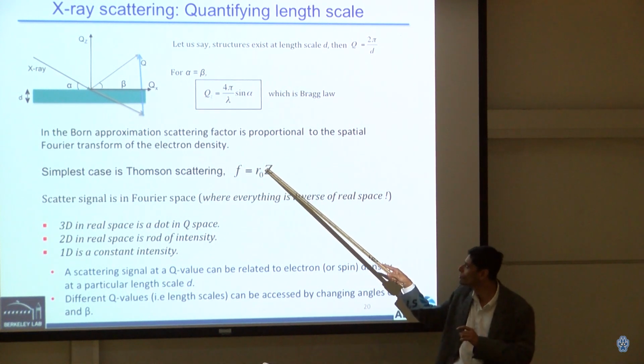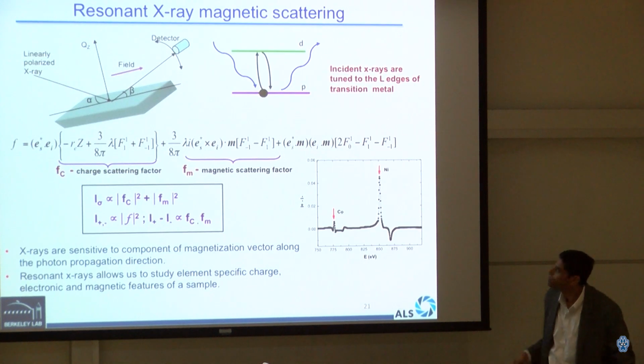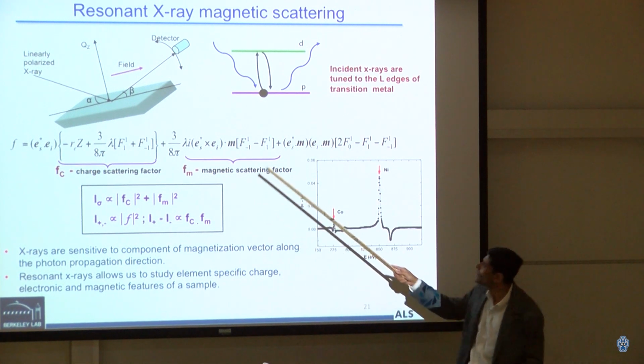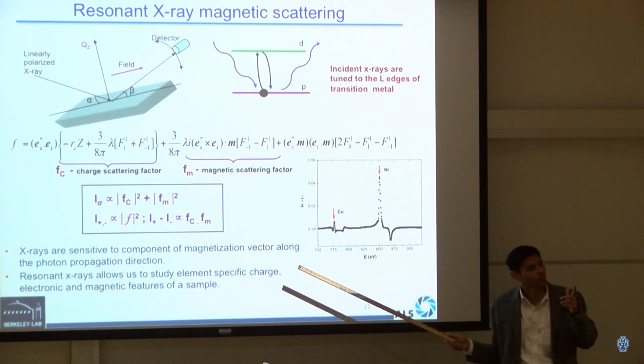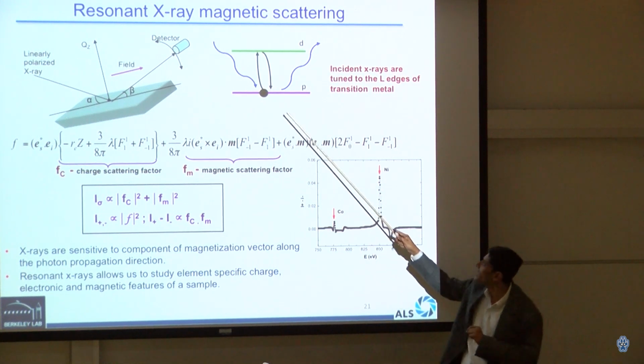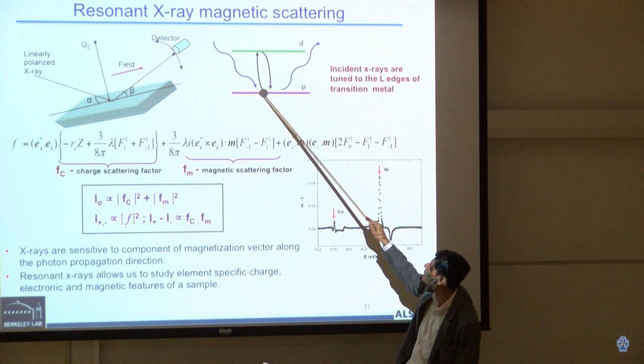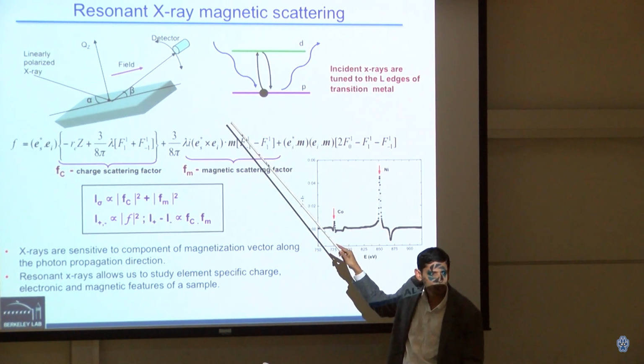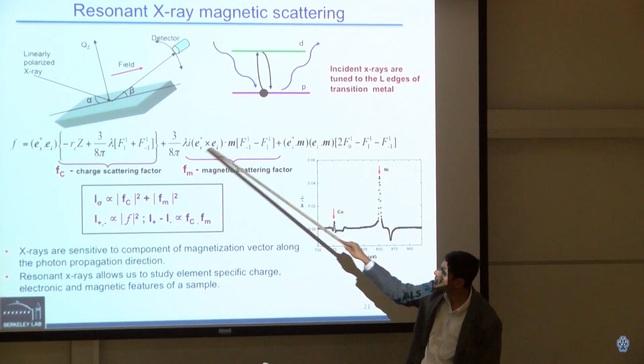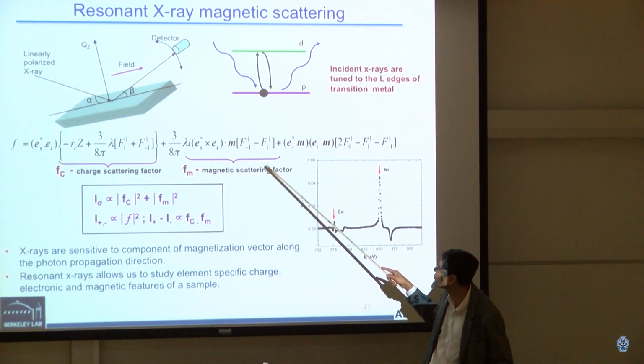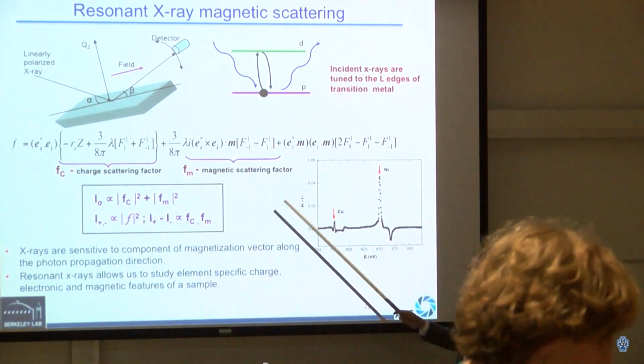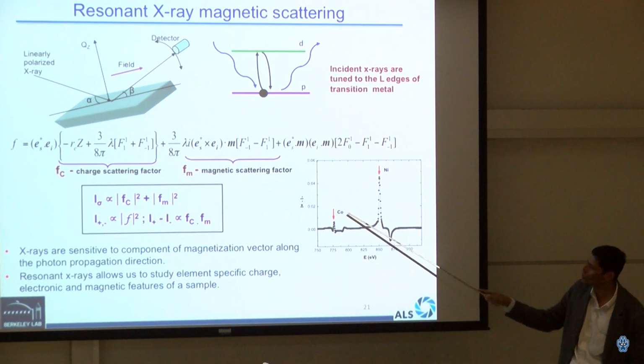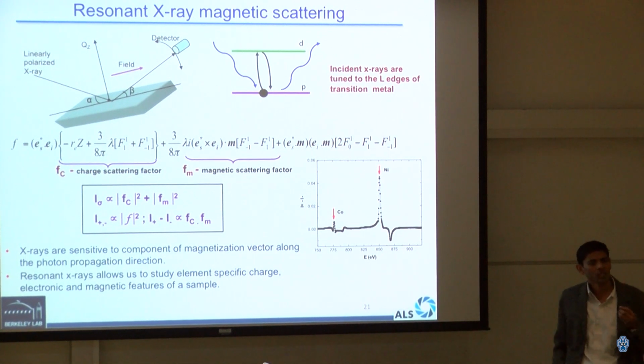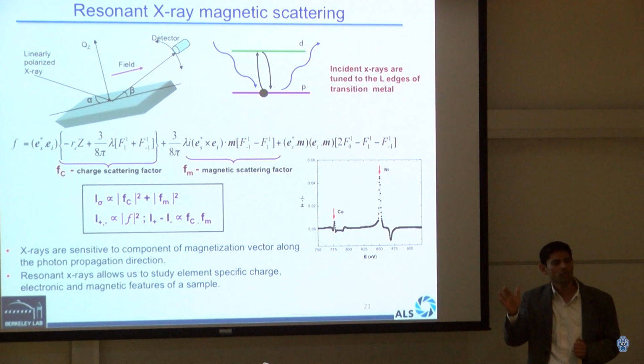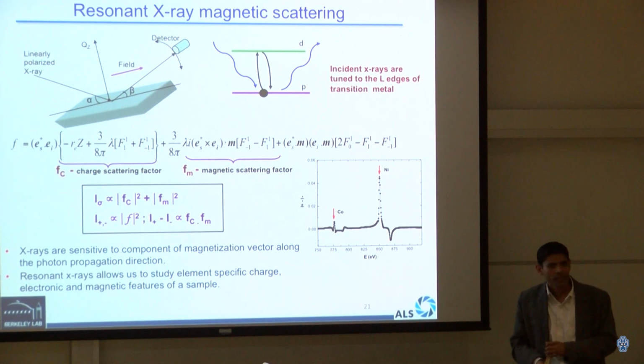It's all Z number. To get to magnetic sensitivity, we have to get to this kind of complicated resonant X-ray scattering where the beam has to be tuned in a way, that's where the synchrotron comes in again. Remember I said there's a tunability, such that the energy of the beam makes a transition from a P core level to an outer D shell and then comes back. And when that happens, suddenly the scattering factor becomes horribly complicated. I'm not expecting any one of you to go over it. Just think that there is now a magnetic term and now you get sensitivity to nickel and cobalt, which are magnetic materials. So ultimately, we have to come with an incident beam that is resonantly coupling to one of the elements, and then we should be able to see.